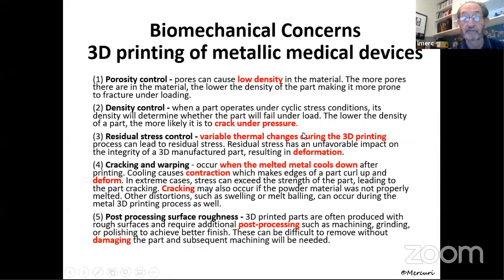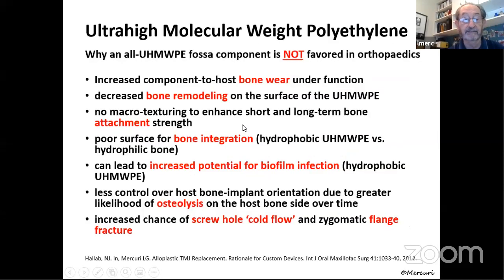The variable thermal changes that occur during 3D printing because of the laser and the way it hits the melted metal, you can get deformation. So 3D printing, while it's a great idea, is still in its infancy. And we have a nice study going on in our lab now looking at 3D printed orthopedic devices. And using the electron backscatter diffraction, we found that some of the spine devices that are 3D printed are cracking because of this low density. So it's not, to make a pun, it's not all it's cracked up to be.